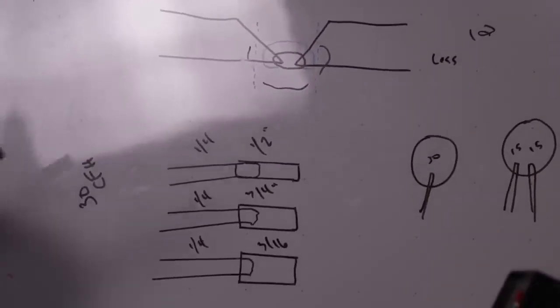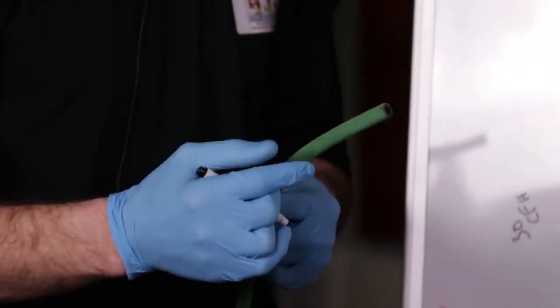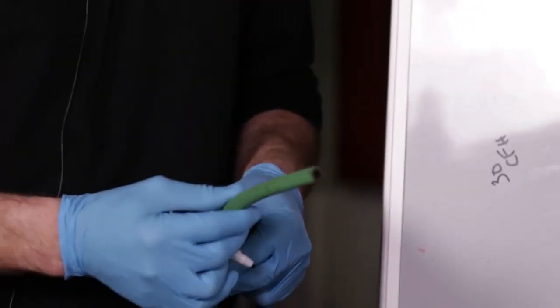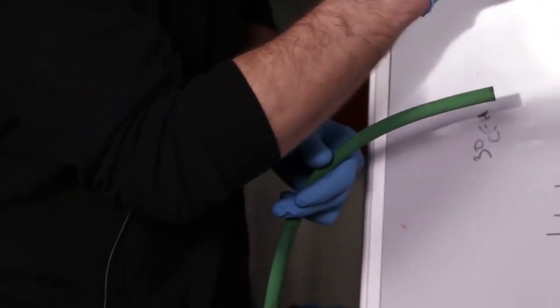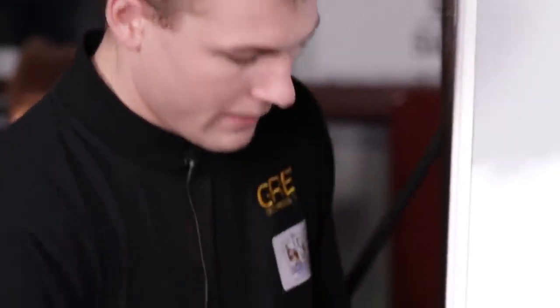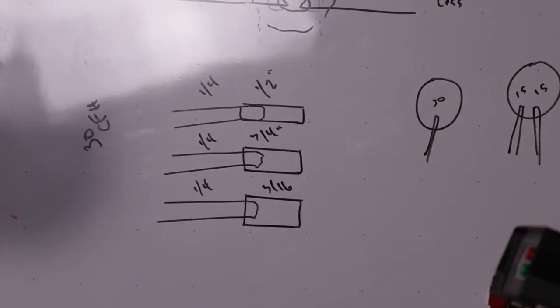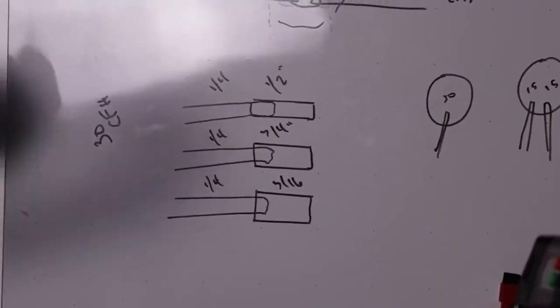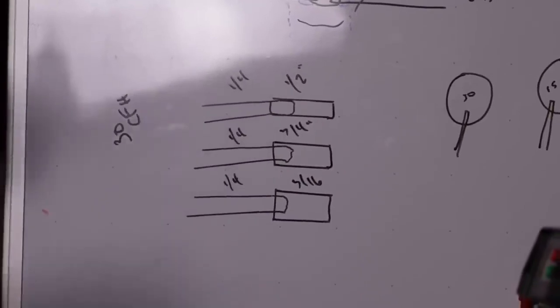Okay. And also, last thing is that usually when you're purging, and this is something that Jerry at JB College of Welding showed me, and this is the reason why I always go to him all the time. Quite often, I'll go in there and say I'm doing a 20-inch or a 30-inch or 8-inch pipe, and I'll tell him what kind of metal I'm welding. And quite often he'll tell me, okay, Travis, use this, and he'll either draw it on the board or physically show me a hose, and he'll give me charts. There are charts for 2-inch, 3-inch, 4-inch, 6 and 12-inch. There are charts that show the number of hoses you use, the size of the ID of the hose that you use, and also turbulence.